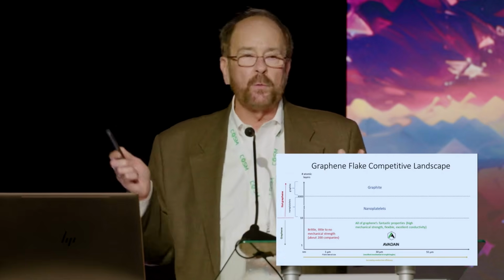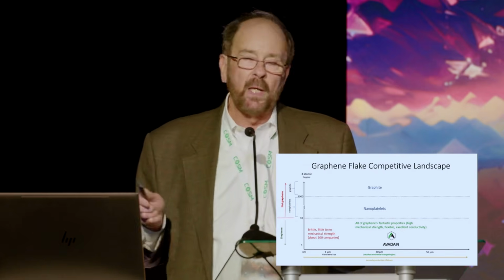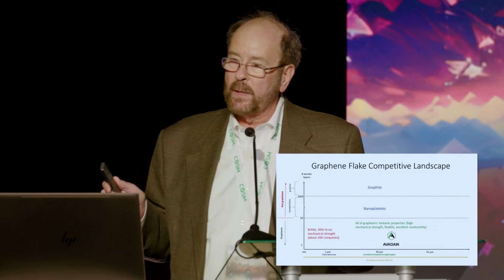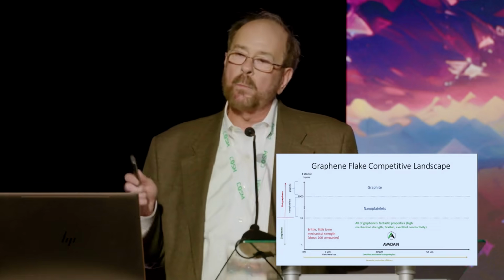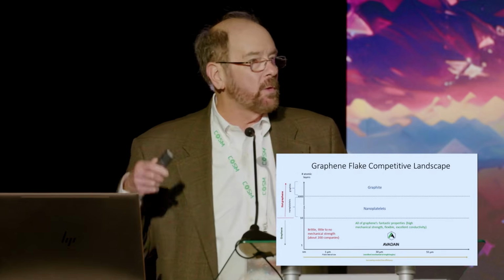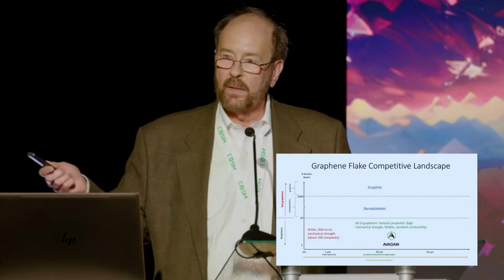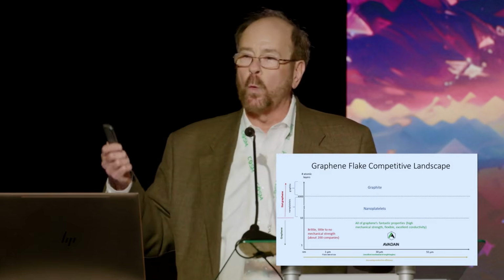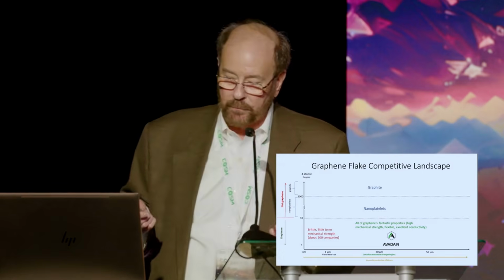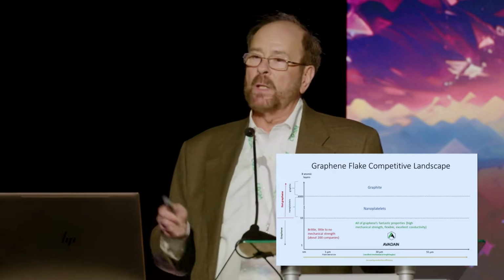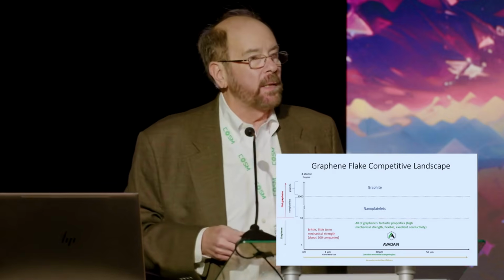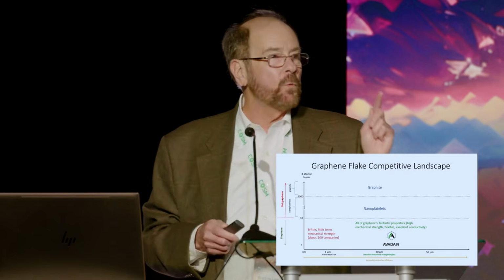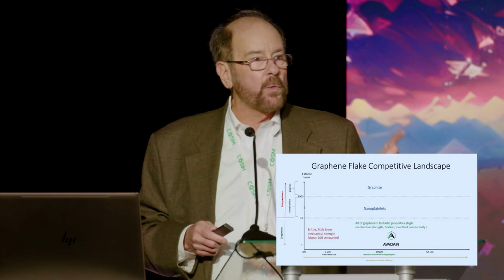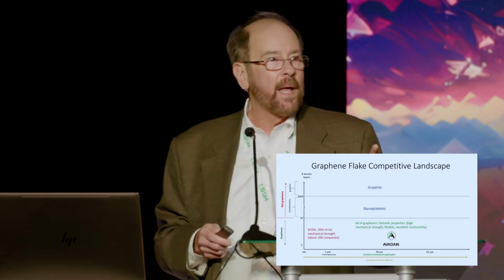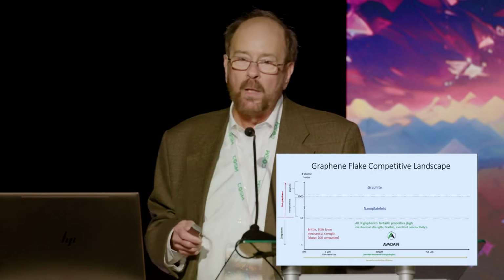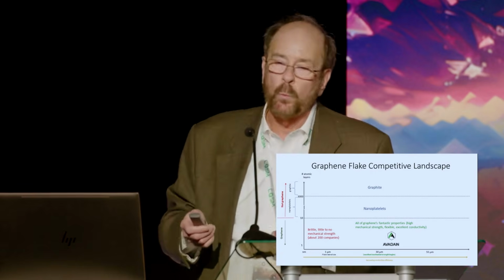And 2.5 years ago, when we first started dealing with the Department of Defense, they were very wary about graphene. The reason is they tried it in ballistic protection. And instead of being 200 times stronger than steel, it was brittle. It shattered. It couldn't be used for realistic ballistic protection. And then along came the German company Bosch. They did a 3-year study, and it concluded that graphene can replace copper. But the larger the lateral flake size of the graphene, the better the electrical conductivity. So these are the things that we tried to address in the work that we did.